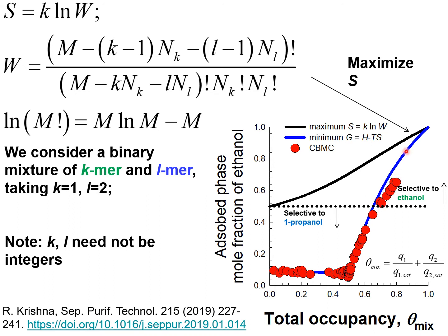Incidentally, this blue line is determined by combining the entropy effects with the Boltzmann expression for S, with an expression for the enthalpy of adsorption determined from the binding strengths. These are not IAST calculations, but the resulting curve corresponds nearly with the IAST.